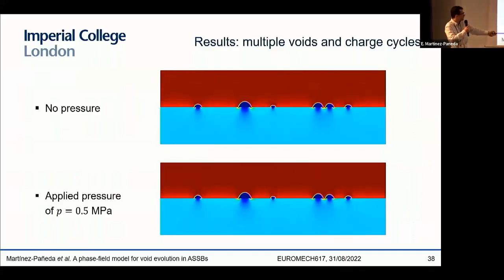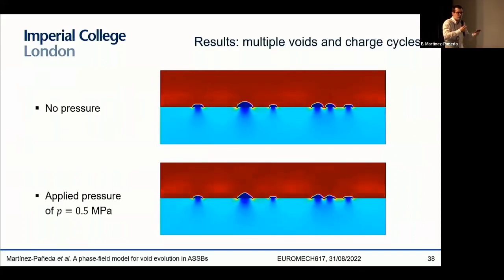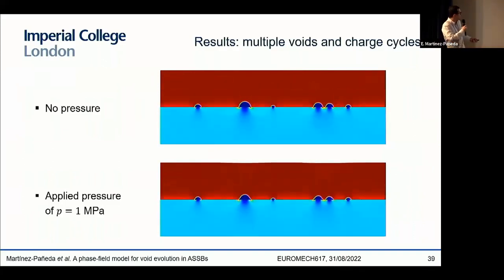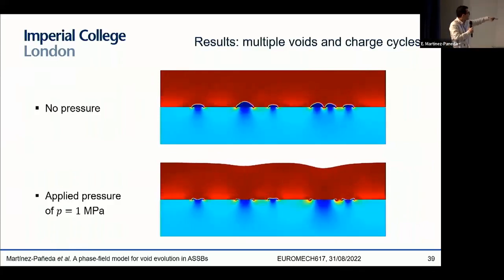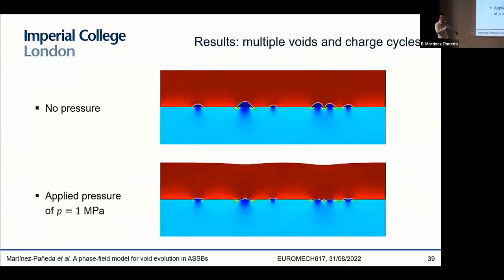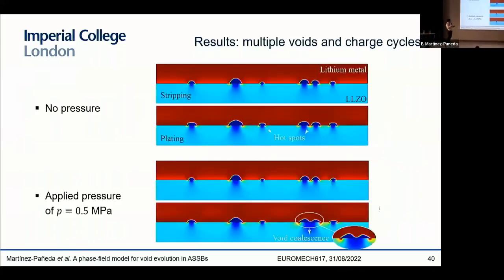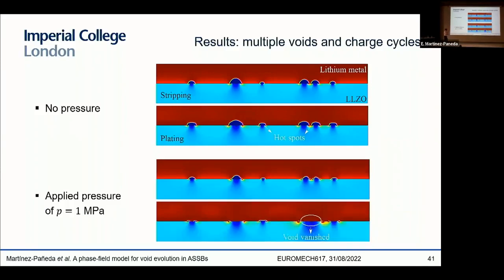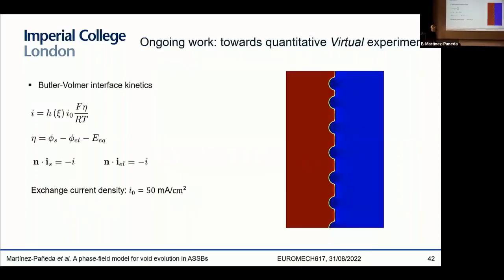You eventually get some sort of void coalescence in there. So the model can capture naturally this kind of interaction between multiple voids. You can see here the case of 1 megapascal, where you can see that actually some of the voids are disappearing from the interface. So this is kind of what you expect from the experiments. And you can see here some pictures of those videos. So in the absence of pressure, here you can see the hotspots formed there, and here, upon the application of a pressure of 0.5 megapascals, you can see phenomena such as void coalescence, which have made these hotspots disappear, for example. And here you can see, for an applied pressure of 1 megapascal, where some of the voids are vanishing there. And this is basically how far we got for our JMPS paper.